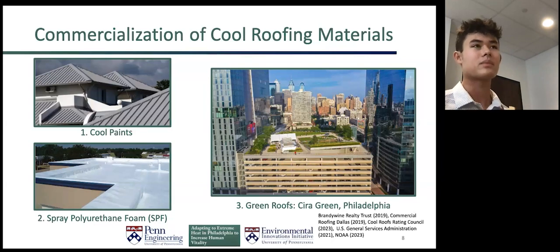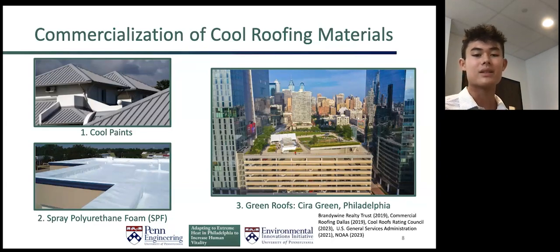incident solar energy. And then the next approach that's been used is spray coatings like this spray polyurethane foam. And that combines the reflectivity of cool paints with insulation. The porosity of the spray foam coating provides an insulating barrier between the hot outside and then the air conditioned interior, which can save more energy.